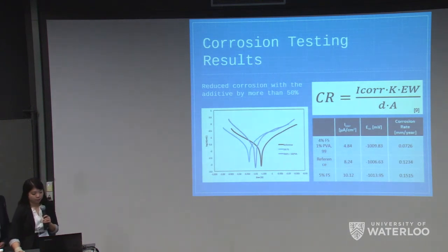The corrosion test is done by measuring the current with a range of voltage. The left side of the curve represents the anodic current, and the right side represents the cathodic current. This implies that the equilibrium is reached when the current reaches the peak at the bottom of the graph as seen above. And by using the Tafel analysis method, the corrosion current was also determined. And the lower the current, the less corrosion that occurs.